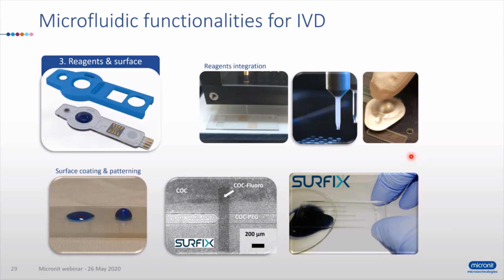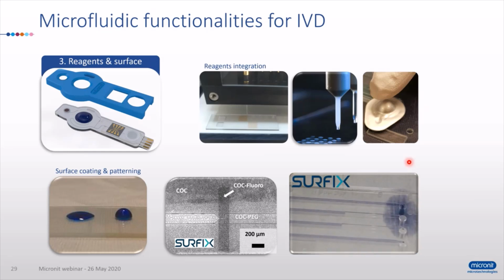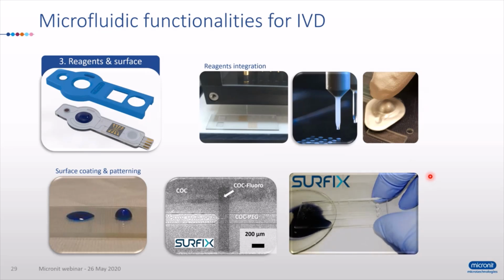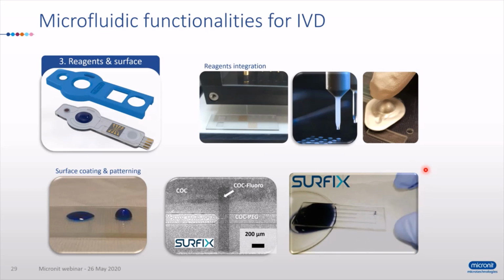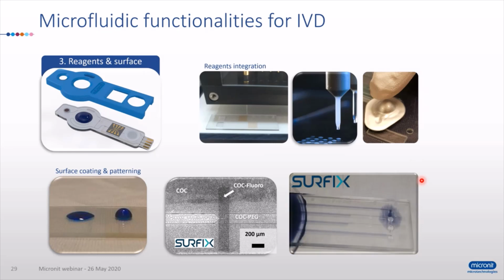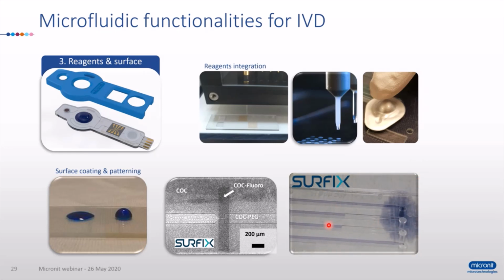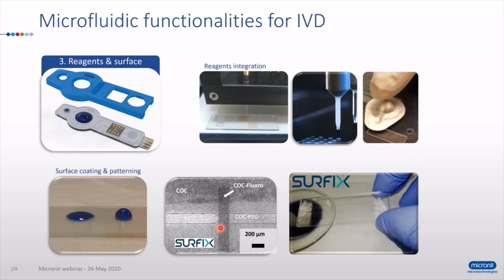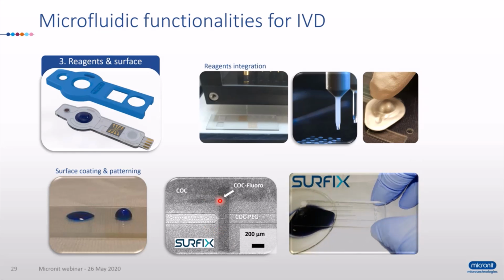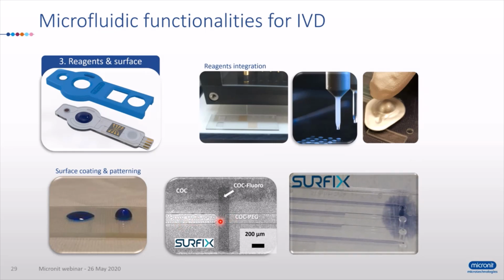Surface functionalization is important for a number of reasons. Anti-fouling properties are very important to prevent fouling of the surface or losing the analyte of interest. But also the contact angle needs to be, in some cases, very well controlled. Think of the capillary-based flow elements or devices that we've seen in the previous slide. Here in this movie and in this image here, you see some demonstrators that were developed by Surfix, this one in collaboration with us in the CoDe Pocket project, where you can clearly see the channel with a capillary stop valve and different kinds of coating.